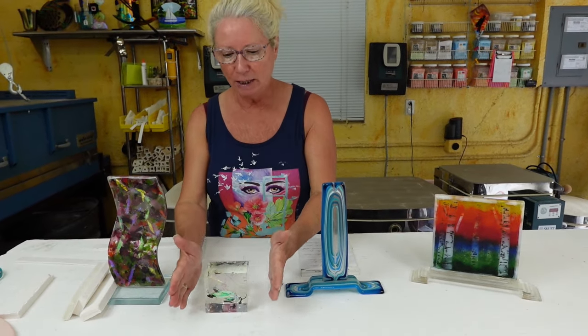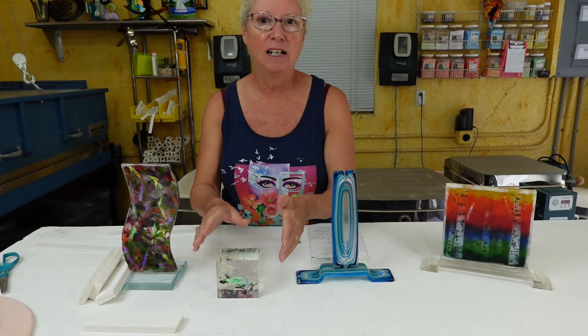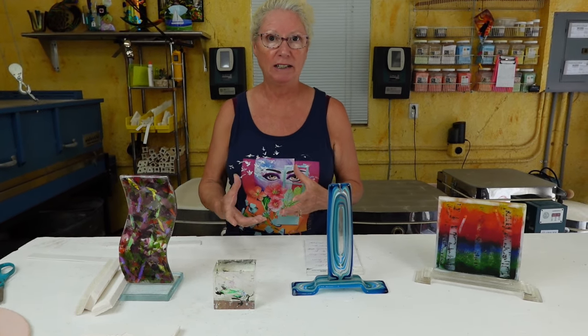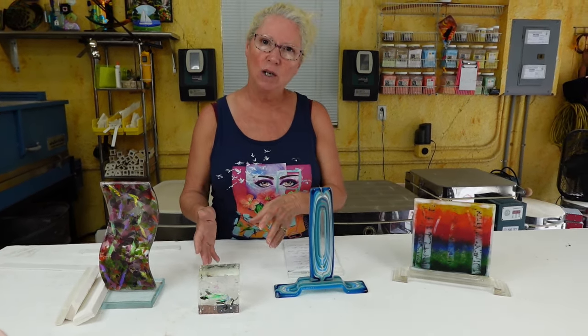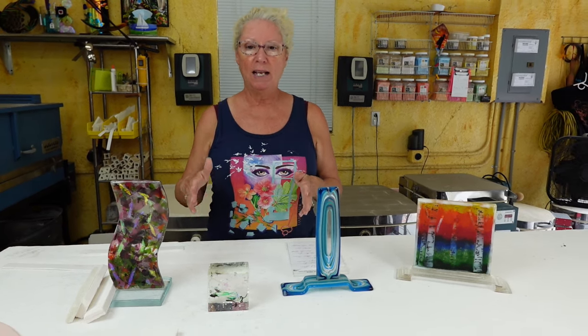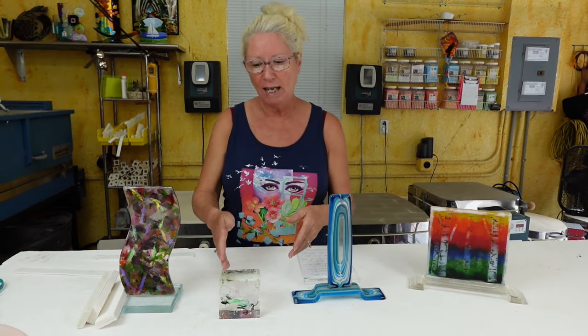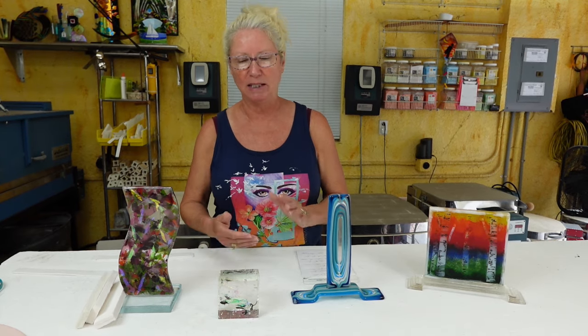This project was created by making a box — I used fiberboard material, but larger. I created a box, filled it with material, and then fired it. This was also a five-day firing because it's so big and thick. This one definitely needed cold working when it came out. Cold working is when you take the glass — the edge quality isn't really shiny. On a cast piece, you really need a perfectly shiny glass edge in order to look into the artwork and see all that spectacular design detail. So I have a 12-inch grinder polisher and I start out with the heavy material, grind it to even out the edge, then go to a lighter medium grit wheel to take those scratches out, and continually go down until we get to a polishing wheel and polish it to a shine where you can see through it and get that spectacular depth and clarity.